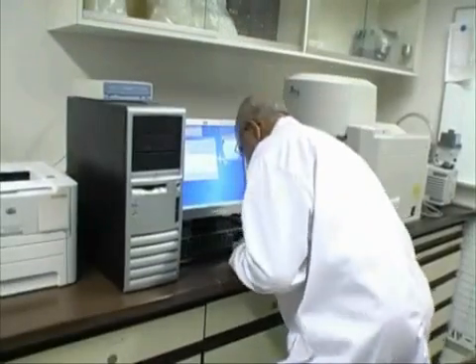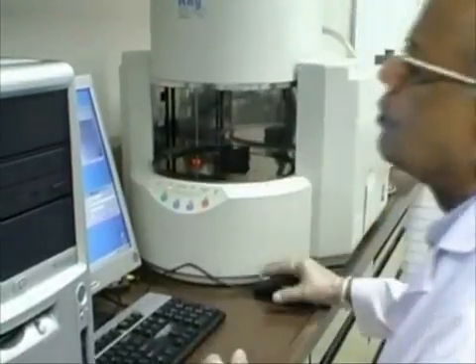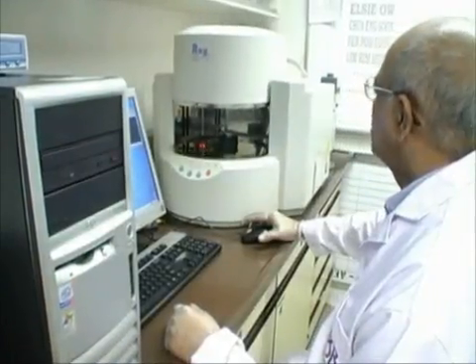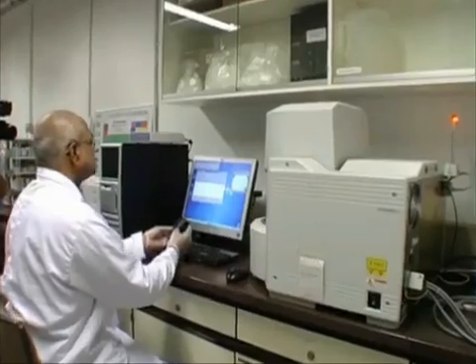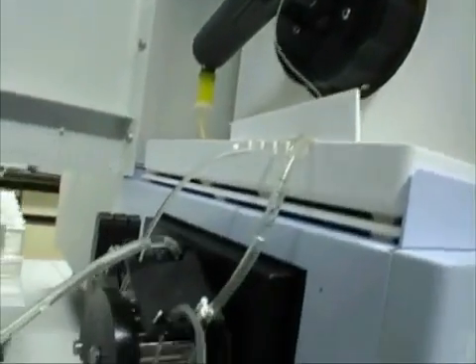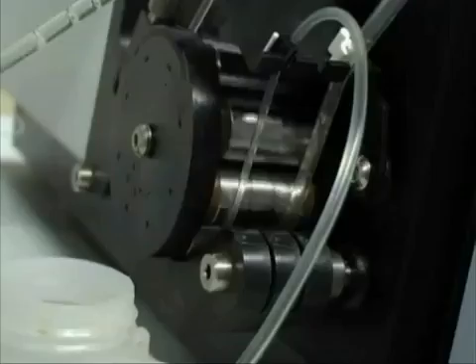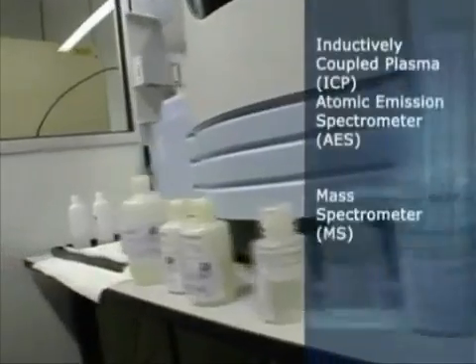Next, the unit undergoes testing for the presence of banned metals such as lead and cadmium to comply with the restriction on the use of hazardous substances. At a macroscopic level, the X-ray fluorescent spectrometer does a quantitative screening for the 4 heavy metals and bromine. For a finer analysis of trace elements down to parts per million or trillion level, the unit is tested using inductively coupled plasma atomic emission spectrometer and mass spectrometer equipment.